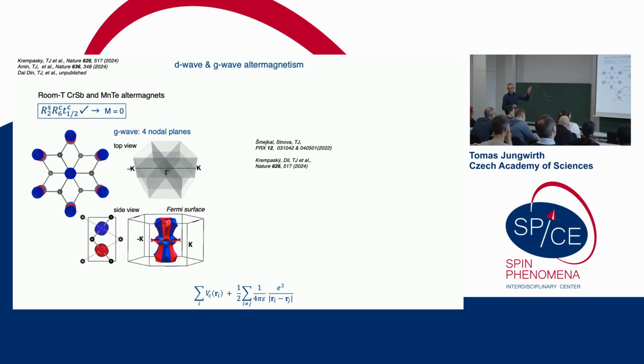So that has been studied in these earlier papers, also by spin and angular resolved photoemission experiments. But there is one important limitation if you go beyond D-wave. If you go to the higher symmetry ones, G-wave or I-wave, the bulk electrical current is not spin polarized. And independent of where you apply the bias, if you go to G-wave or I-wave, the electrical current is not polarized.